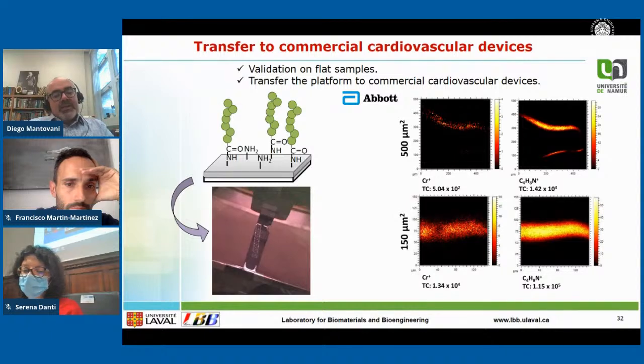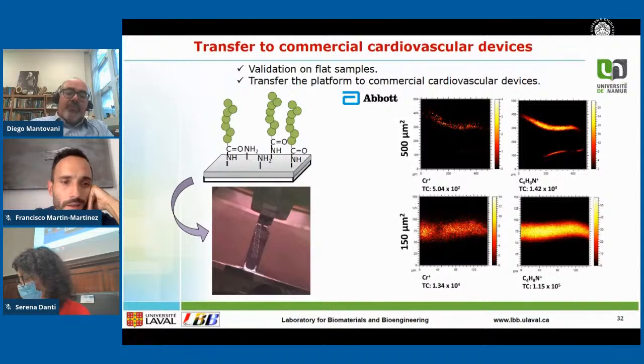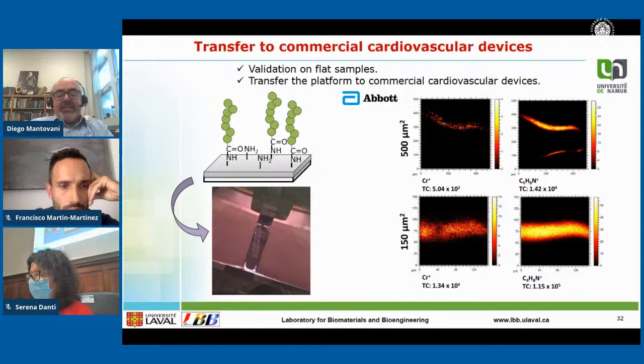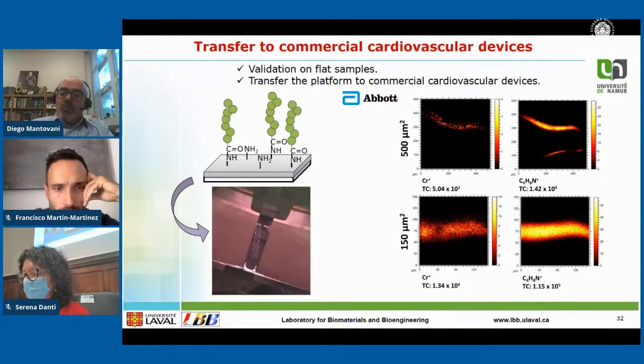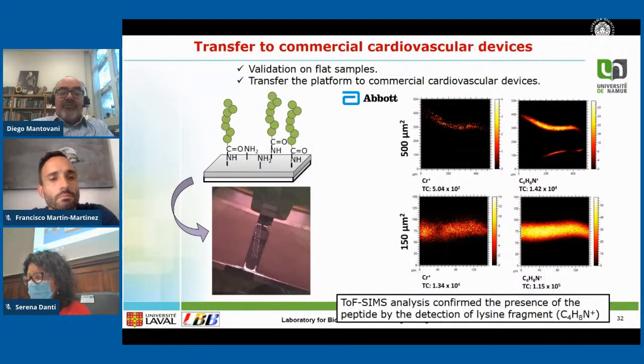Can you imagine doing XPS? Can you imagine doing contact angle, surface profilometry? Everything becomes more complex. And when the challenge becomes high, you need to use very advanced techniques. So we went to TOF-SIMS imaging, and this is an image obtained on 500 micrometer square and 150, and what you see in yellow is basically the presence of P8RI on the stent structures, because Abbott wanted to be convinced that the peptide was really grafted. TOF-SIMS analysis confirmed the presence of the peptide by detection of the lysine fragment C4H8N positive ions.